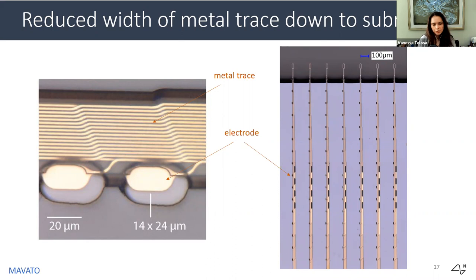The second knob we turned was we increased the number of metal and insulation layers. These probes, starting out with one layer, are only about 4 microns thick to begin with. So we have a lot of room in the Z direction to increase. Instead of putting the metal traces side by side, making the probe wider, we started stacking them on top of each other. You can kind of see it in this image here. There's another layer of arrays or traces just underneath.